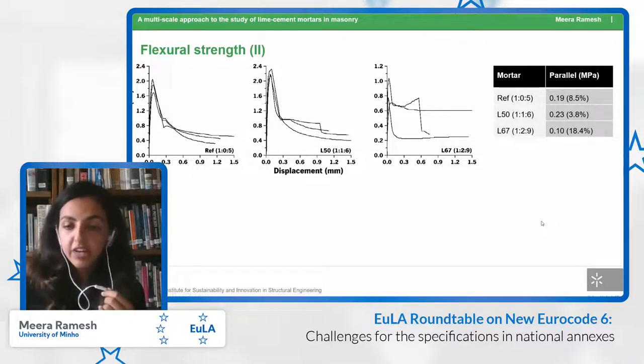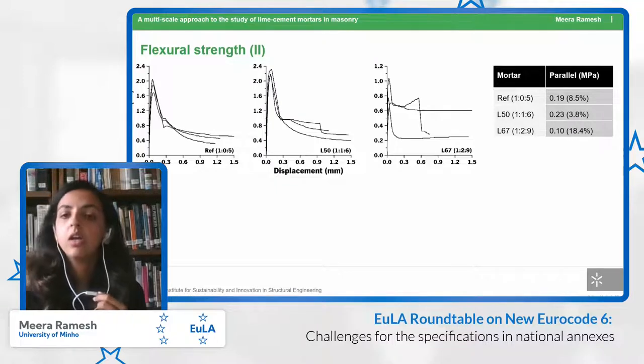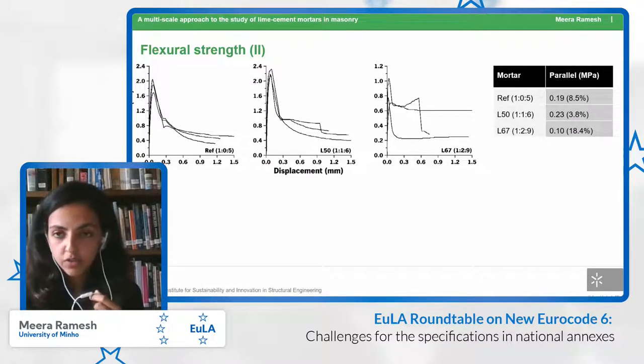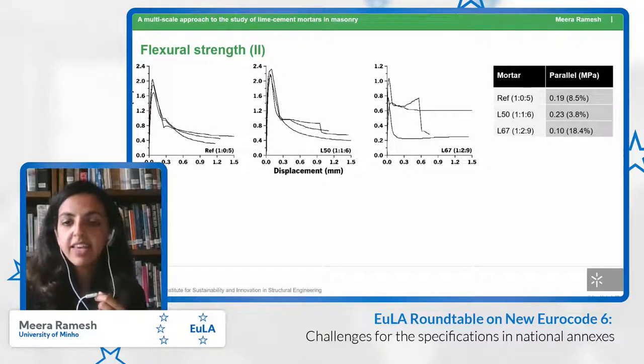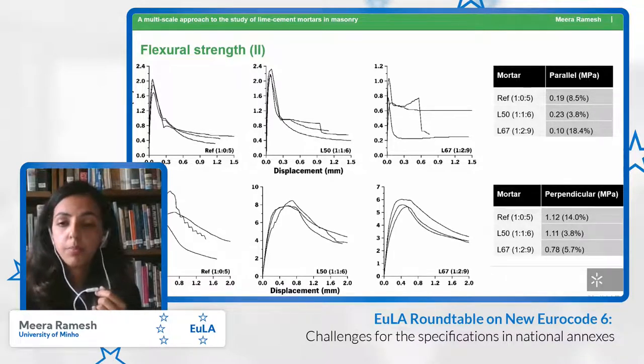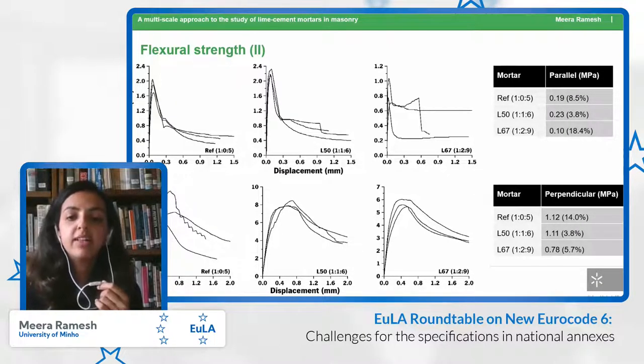In the parallel direction, we found that the mixes which had similar strength, the reference mix and L50, gave us similar values of flexural strength at the masonry level, whereas L67 was much lower. Similarly, in the perpendicular direction, the reference mix and L50 gave a similar flexural strength, whereas L67 gave a slightly lower flexural strength.